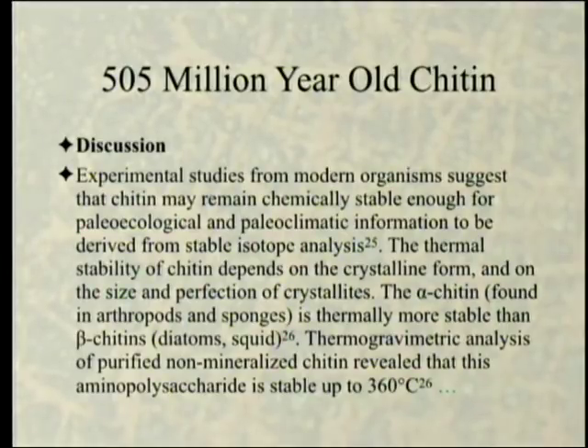Thermogravimetric analyses of purified non-mineralized chitin revealed that this aminopolysaccharide is stable up to 360 degrees centigrade. You know what that is in Fahrenheit? 680. In other words, they baked this thing like crazy.